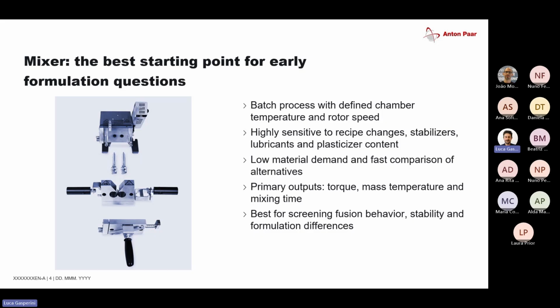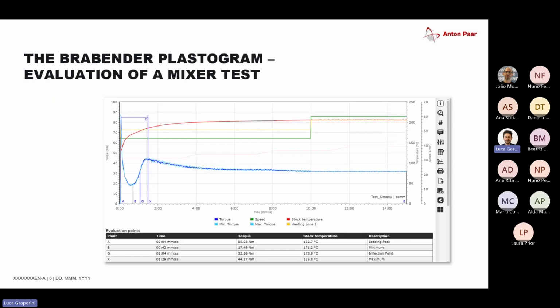For example, the measuring mixer is used when you think about PVC applications, and PVC in itself is a very special polymer as it doesn't really melt. It has this fusion or gelation process where you have different stages of particles which melt but fuse together to form a three-dimensional network of particles. An example curve of a fusion process you can see right here. This was done in a measuring mixer.